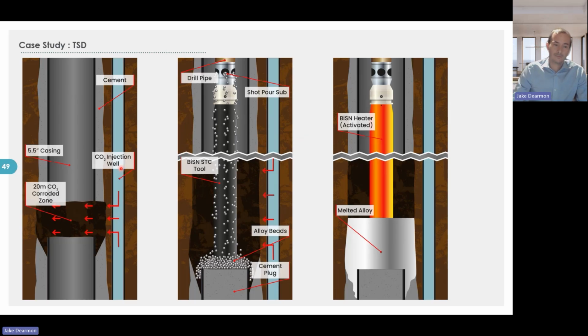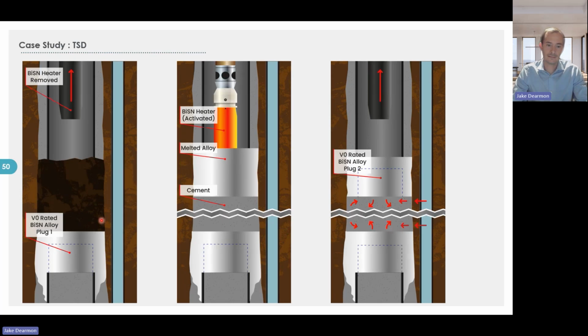What we're able to do here, we can see where this lithology zone that the CO2 was flooding in from had completely corroded this casing. We're able to run a log and see where that zone was. Design some tools to be able to seal down in the open hole below that interval of CO2 injection. We set the plug, removed the heater. We then needed a sacrificial spacer because we did not want to put 20 meters of bismuth in the well. So we put cement over that CO2 zone and set another bismuth alloy in the formation directly above that. So you ended up with a straddle that protected the lower wellbore from the upper wellbore.